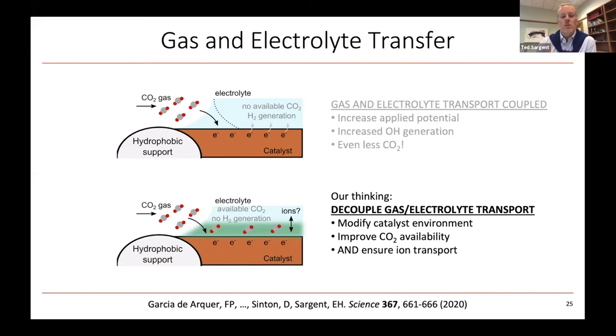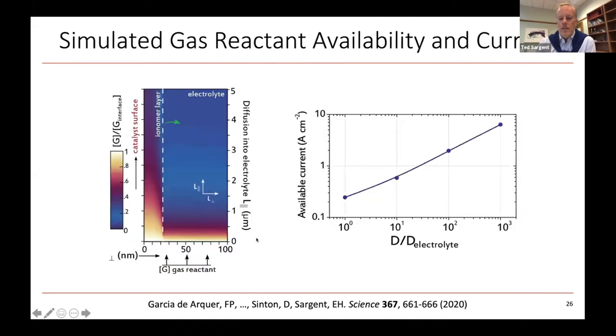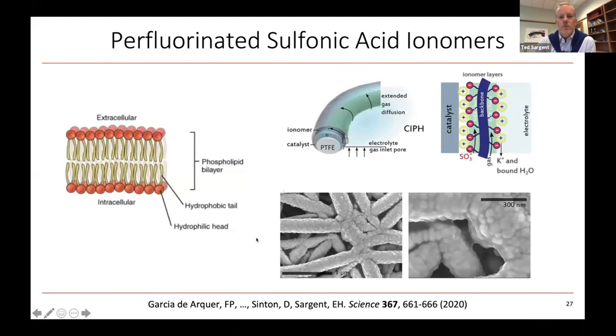Some kind of material that would kind of assist in the transport of the CO2 gas and would do so very selectively right along the heterogeneous electrocatalyst surface. So we'd kind of have a transport medium that would wick our ingredients, our reagents, right along the desired boundary. And so the way in which we ended up doing that was using perfluorinated sulfonic acid ionomers. So PFSA or Nafion is where we put our focus.